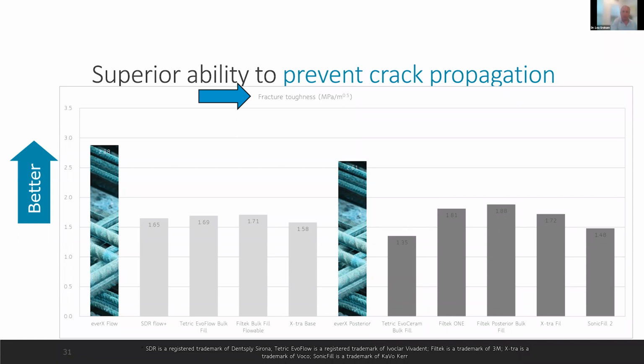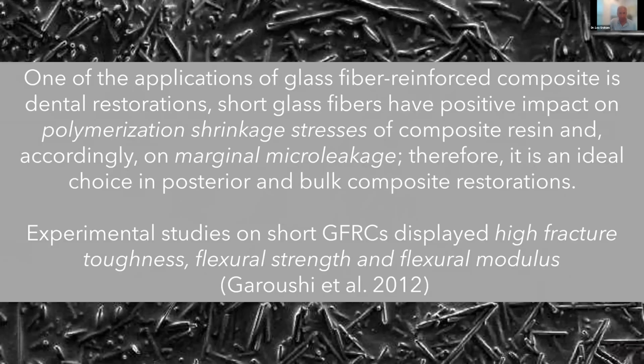So again, we're going to walk you through how we use this material. And in many ways, it's replaced challenging posts where I may want to put a post. Like in this case, no way was I going to put a post, or in large core buildups. And this is just a routine product when I'm rebuilding teeth. So one of the applications, and you'll see in the literature, again by the same author 5 years later, is that they also have a positive impact by decreasing polymerization shrinkage stress. So if you have less shrinkage stress, basically less marginal microleakage, it becomes almost an ideal material to rebuild the core of the tooth.